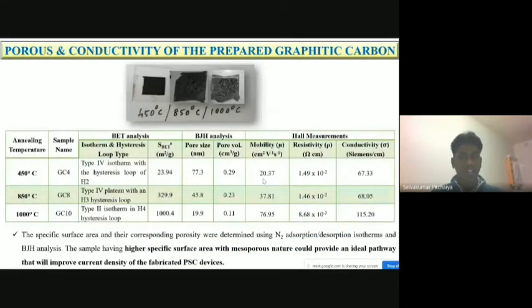And this is the conductivity and the porosity of our prepared material. The higher the temperature, the higher the conductivity. At 1000 degrees Celsius, you can see it has a conductivity of nearly 115 siemens per centimeter, so it is highly conductive. Depositing this layer is also very easy. It's just a brush painting technique. You can easily take a brush and spread it over the films.